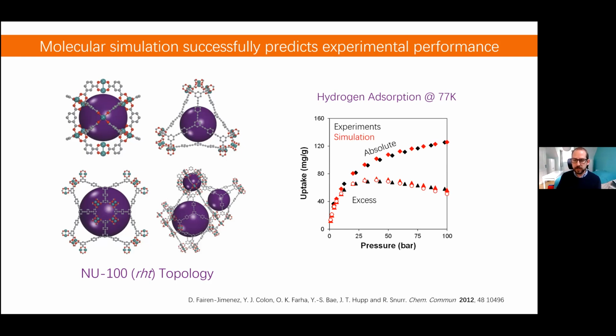Amount adsorbed of hydrogen at 77 Kelvin when we increase the pressure. This curve is the excess amount, and this curve here is the absolute amount. Okay, if you don't really know the difference between absolute and excess, don't worry. This is something important when we are working at high pressure. But basically, what is really critical here is the fact that experiments and simulations really match. Okay, they work really nicely.